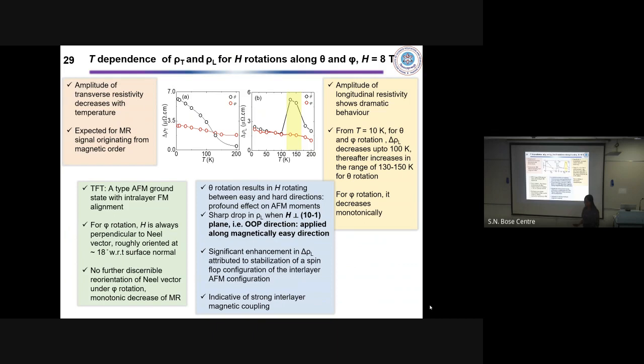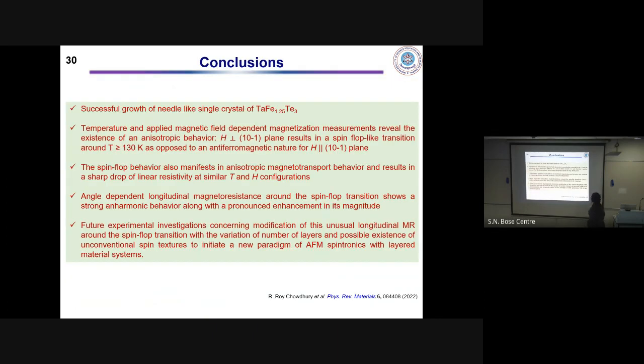coupling in this system. So I would like to conclude that we have grown needle-like single crystals of TaFe1.25Te3, which is a layered antiferromagnetic system. Temperature and applied magnetic field dependent magnetization measurements reveal existence of an anisotropic behavior when the applied magnetic field is applied in the out of plane direction of the crystal.